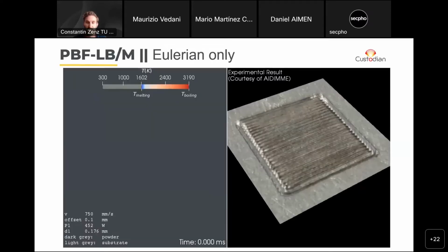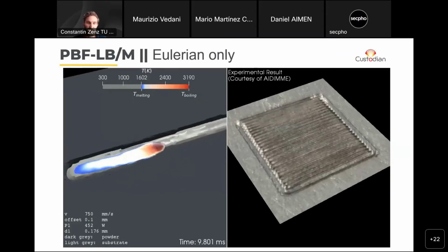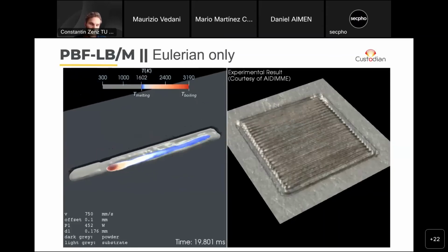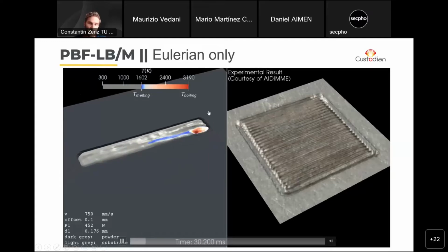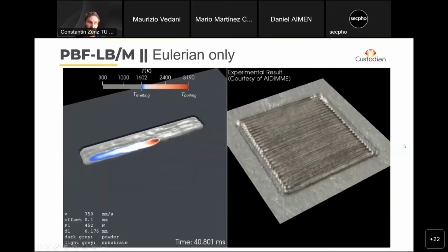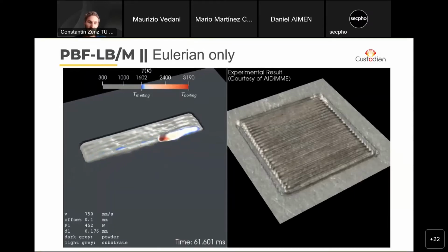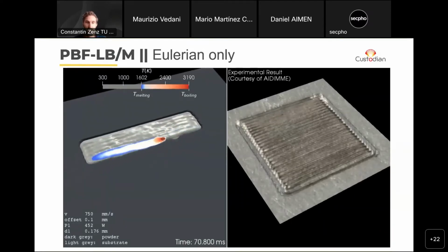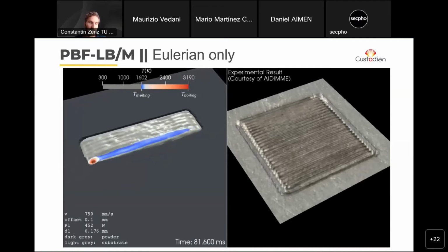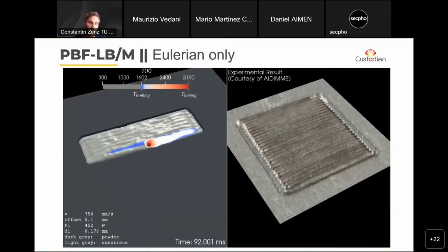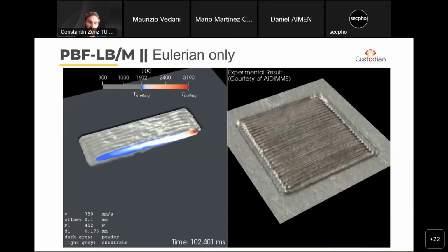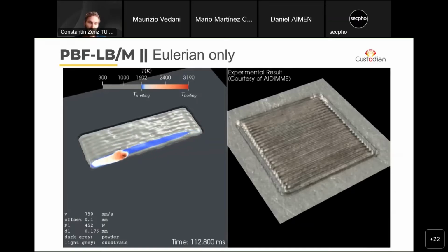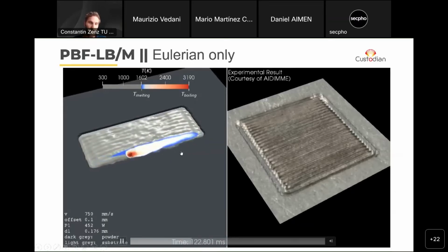So this is what you can see here now. On the right-hand side, this is an experiment performed by AIDIMME. And on the left, you can see a corresponding simulation. And now you can see this dark gray area. This is representing the powder. So it has the same thermal conductivity and density and so on like powder, but we do not have to consider individual particles. And then the laser beam melts this powder, and we can actually see some evaporation also going on, and the melt pool, which is forming.